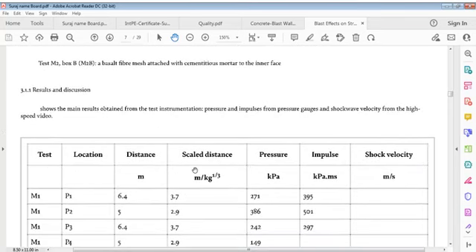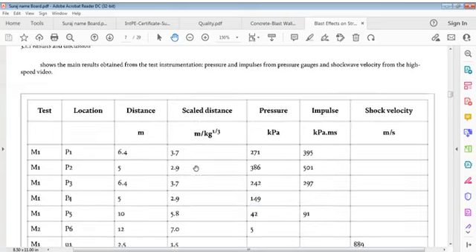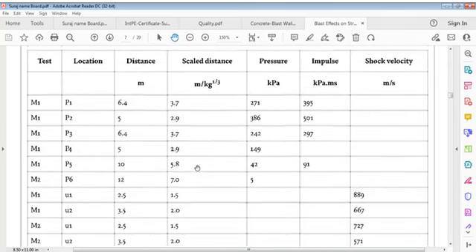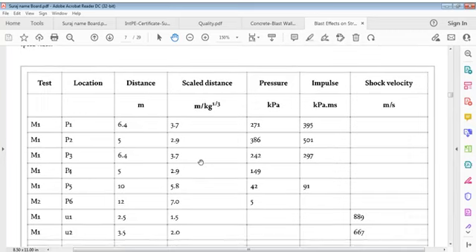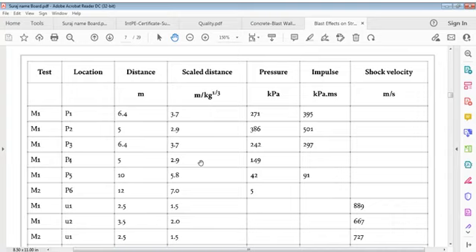The results show the main results. These main results are obtained from test instrumentation: pressure and impulse from pressure gauges and shock wave velocity from high speed video. These are test, location, distance, scale distance, pressure, impulse, shock velocity. Test is M indication, location P indication, distance in meters, scale distance in meters per kilogram to the 1/3, pressure in kPa, impulse in kPa·ms, and shock velocity is here.